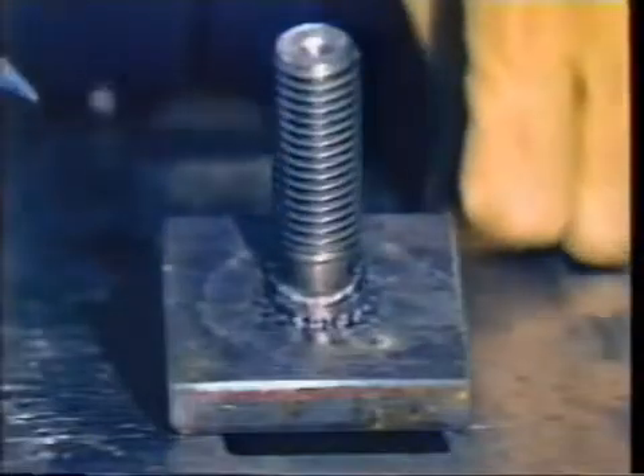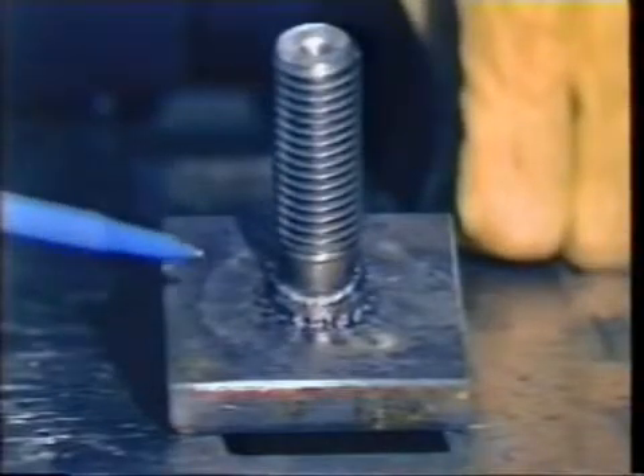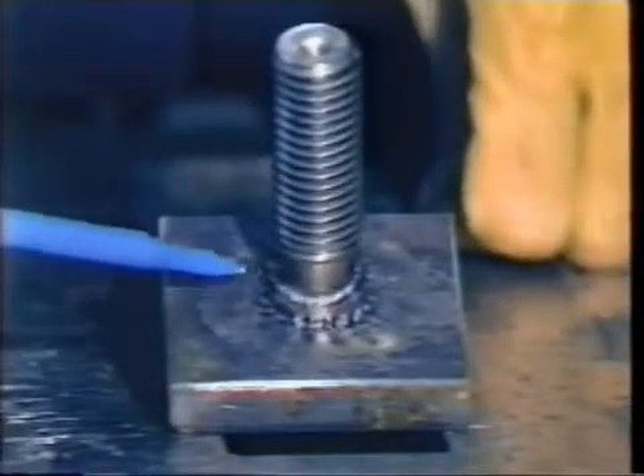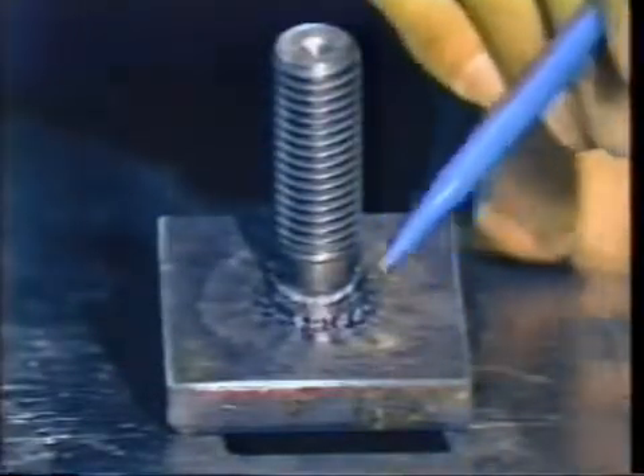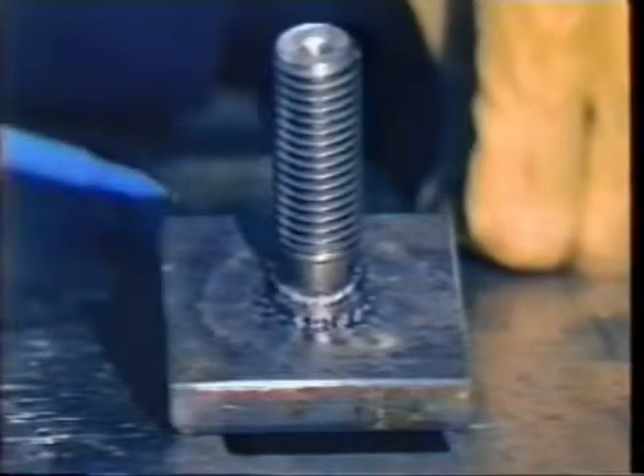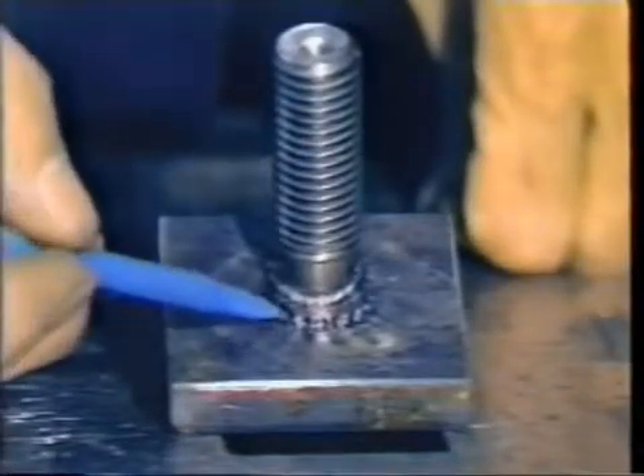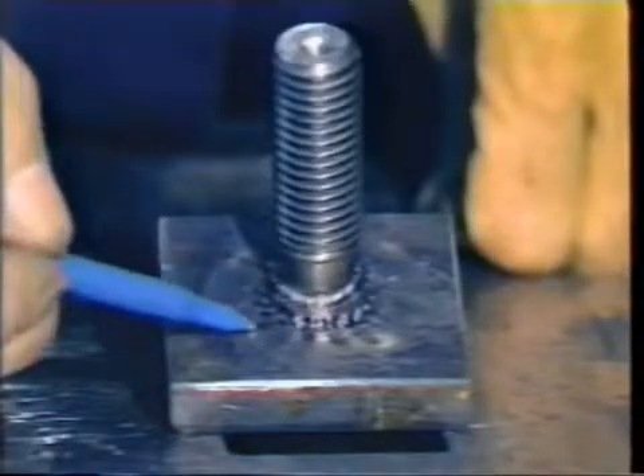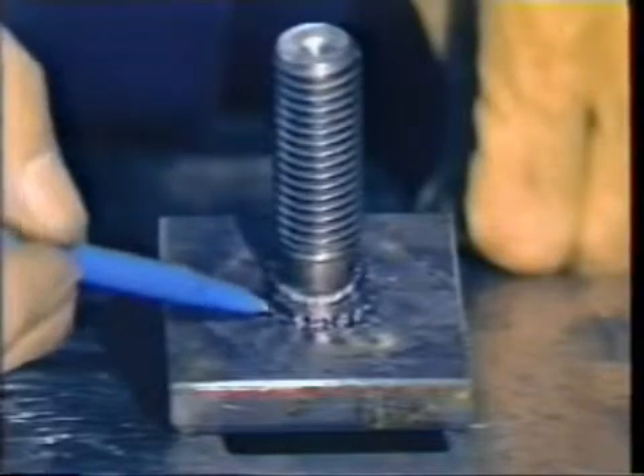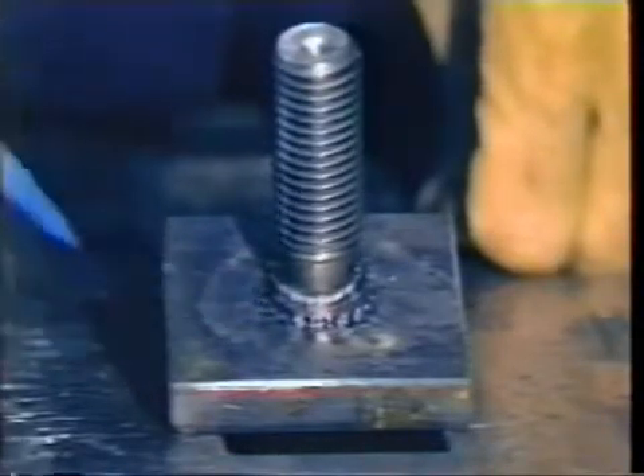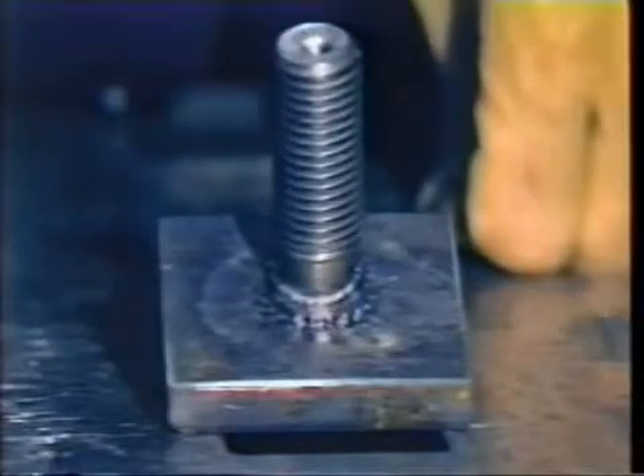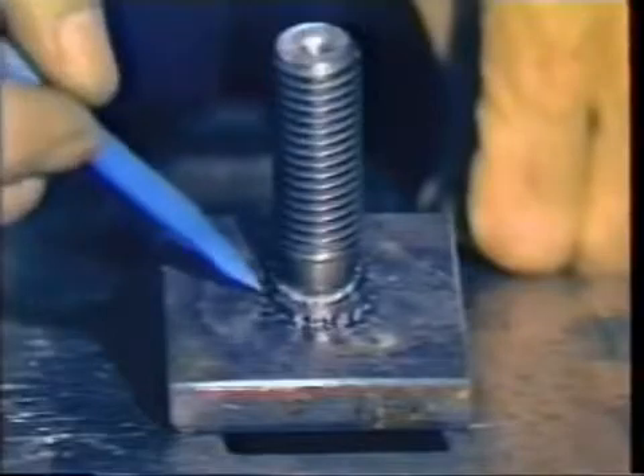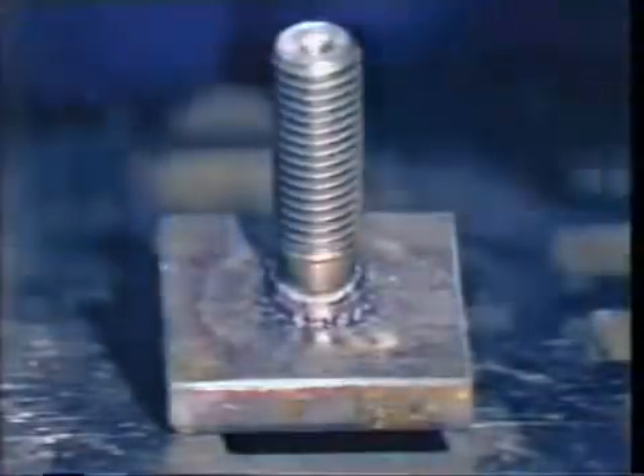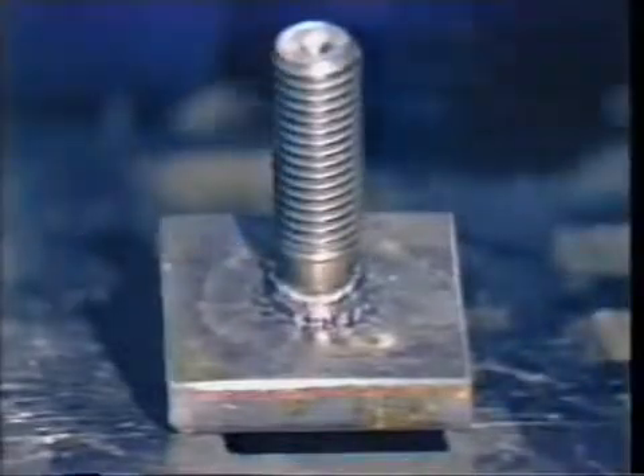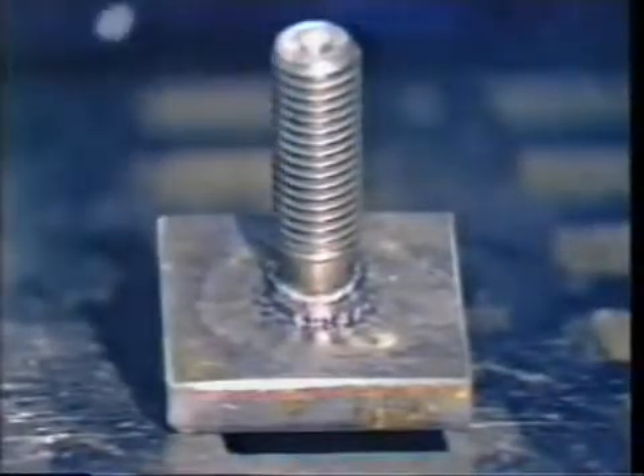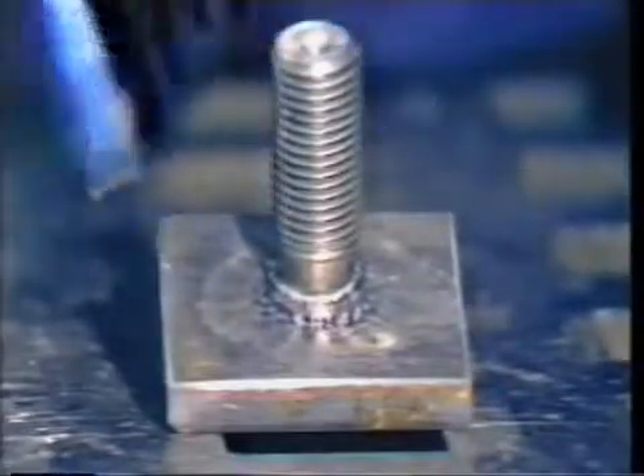A good stud weld onto clean base material is typified by a bright, shiny weld fillet with even height from one side to the other all the way around. The best indicator, though, is a bright junction of the fillet material into the base material. If that junction is a blend, a shiny radius, rather than material that is rolled under in a donut setting on top of the base material, you're then assured that you have bonded metal to the extreme edges of the weld fillet. If the metal is rolled under, you don't know how far under the material is rolled and where bonding begins and ends.